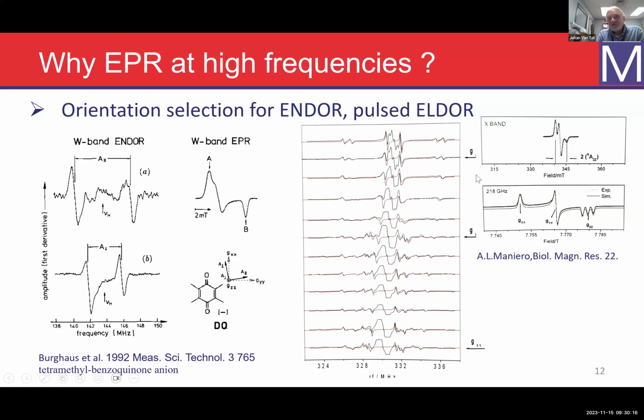But if you go to these high frequencies, even if you don't have a single crystal, you can kind of get single crystal-like results. Of course, you're only at the extreme limits. You're really selecting for a single orientation. In the middle, you always have a range of orientations. But you can see that you can pretty well simulate these different hyperfine couplings to the protons.